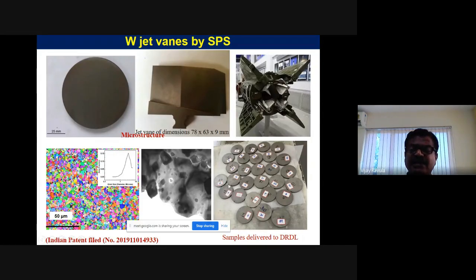But the problem is they need to have good erosion resistance at high temperatures, and good strength, even though the time is only 5 to 6 seconds. Once it takes off and is put in the projection in the direction, then it goes off. So that's only the 5 to 6 seconds it has to withstand. And then we have been interacting with